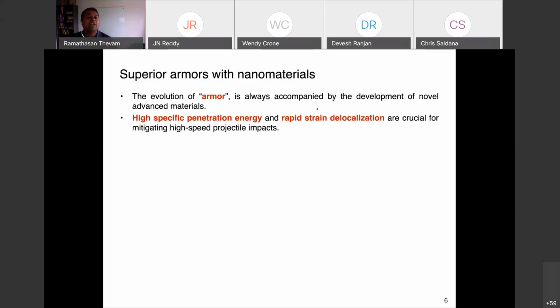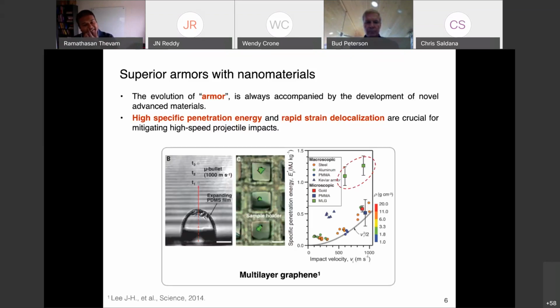So when you think about these armors, there are two things you would like to have. One is high specific penetration energy, so that you can absorb the energy of the projectile. The second is that you want to rapidly delocalize the concentrated stresses from the projectile such that you can avoid localized failures.